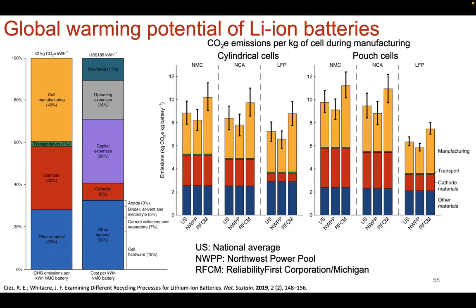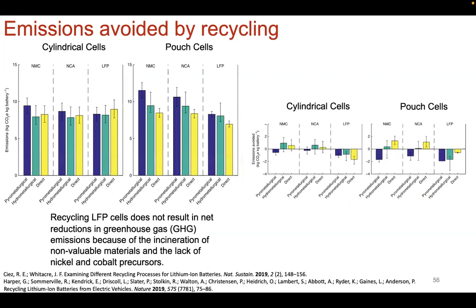Okay, in terms of cell manufacturing and also overall CO2 emission. But pouch cells are higher relative to cylindrical cells when it comes to the other 2 chemistries, so the NMC and NCA chemistry. So it depends what chemistry you're targeting, if the CO2 equivalent is going to be increased or decreased for the 2 configurations. And then once you have these cells, in terms of recycling them, it's also a different story.